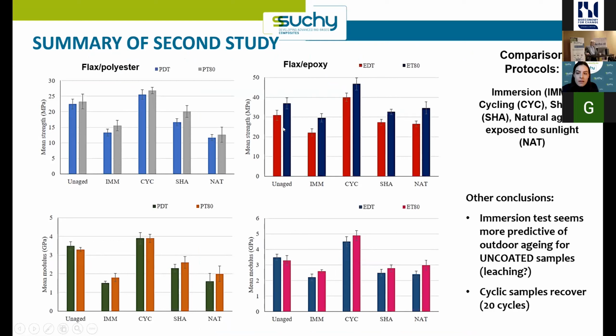And again, in red is when you fully dry the fibers, and in blue is when you don't dry them, actually precondition them, in this case, at 80% humidity. And you see indeed consistently that the idea of not drying the fibers is clearly beneficial. But you also see very interesting differences between the aging protocols. If you see here SHA and NAT, that is the outdoor aging for 10 months. And it appeared that the immersion testing was quite predictive in the end for the behavior, so the quite harsh immersion test.